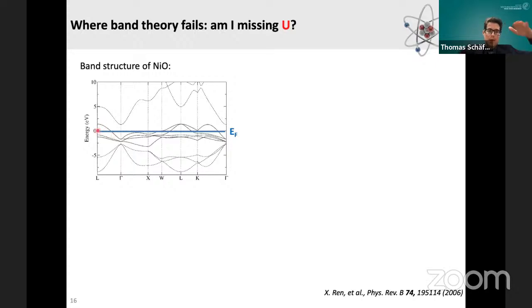so to say, going from the region where we have the unoccupied states to the region where we have occupied states. So they are going through the Fermi level, which means that I can quite easily excite those electrons, namely thermally, to, for example, conduct electricity. So this means, out of the band structure calculation, this nickel oxide should be a metal.